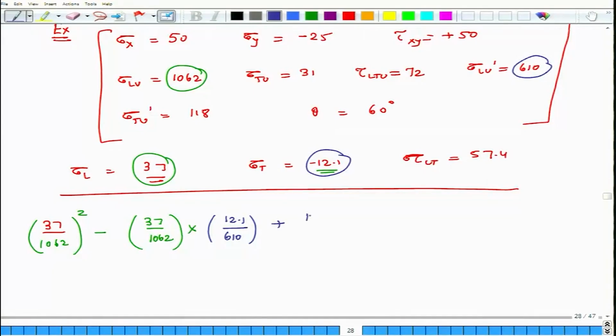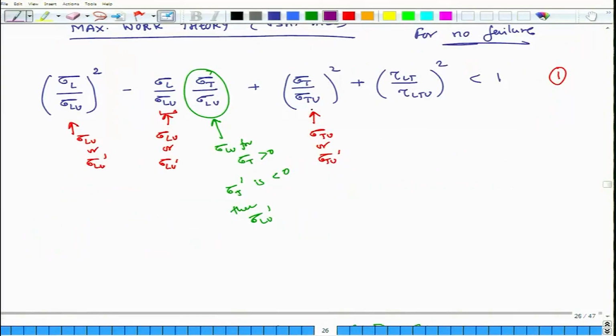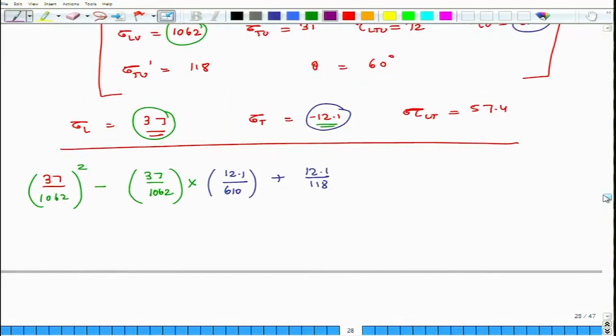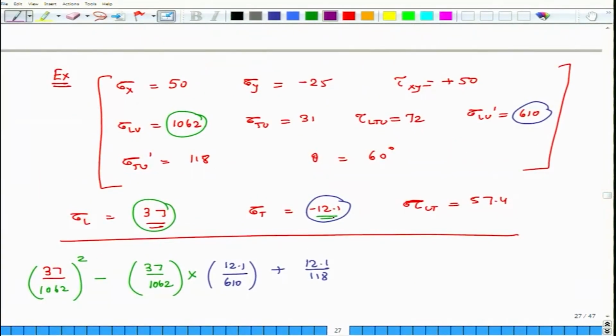And then of course, the third term is 12.1 divided by 118, because the third term says sigma T divided by sigma Tu. So, sigma T is negative 12.1, so we consider sigma Tu prime, which is 118. So, this is squared, and then finally, we have the shear term 57.4 divided by 72, and this works out to be 0.6, which is less than 1. So, the material is safe and will not fail.